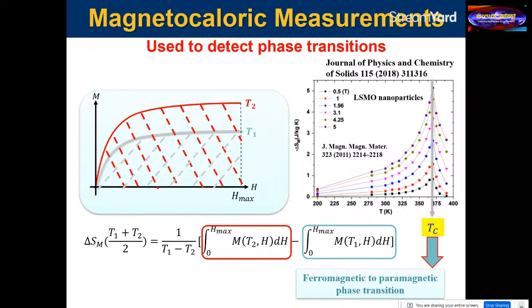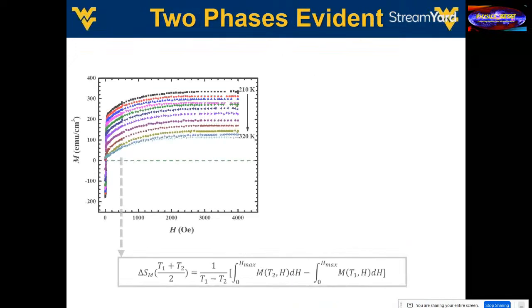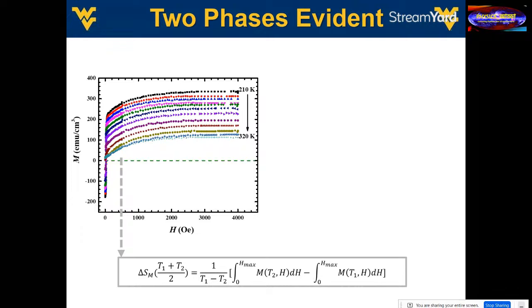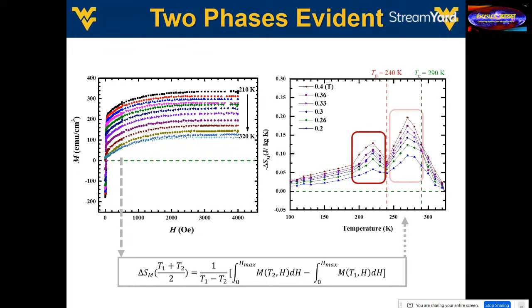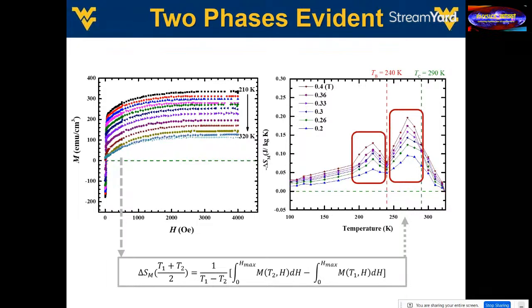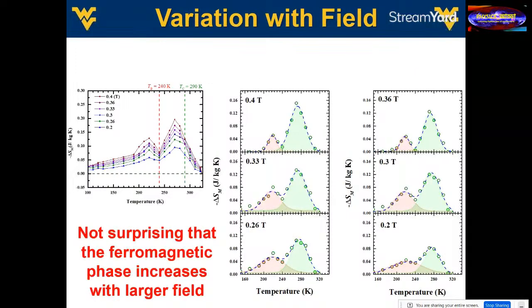All right, so we decided to give it a try in our systems. So here are our original curves, measurements at different temperatures. And what we actually see are two peaks, which come from our two phases. So one of these is the standard transition from ferromagnetism to paramagnetism. And then we have this other phase, which I've mentioned is kind of like a diamagnet. And interestingly, it can show how much of each phase we have. So I've colored them here. So the green is like the ferromagnetic phase, and the red is like this other phase.